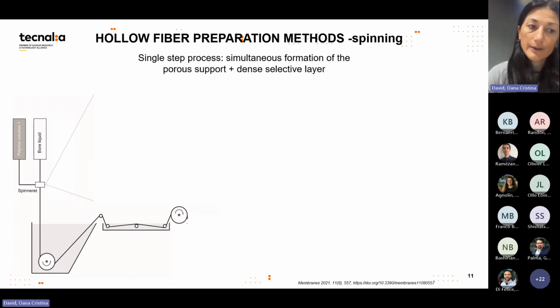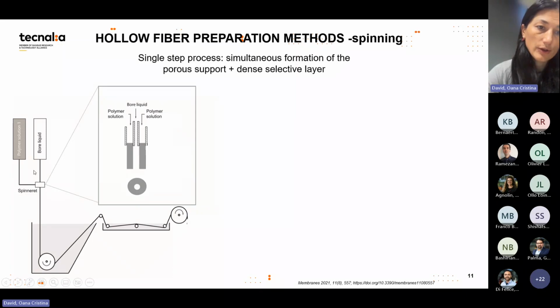So here I very simply show how it's done. We have a polymeric solution that is co-extruded through a spinneret with a bore liquid. The cross-section of the spinneret is shown now. What we have here at the exit of the spinneret is a hollow tube. So this is a polymeric solution in this shape. And we manage to maintain the hole by having a bore liquid that contains a mixture of water and the solvent. And then we have a phase inversion. Before coagulating this structure in a water bath, we can have an air gap where some solvent evaporation on the outside can take place, and I will show later why.